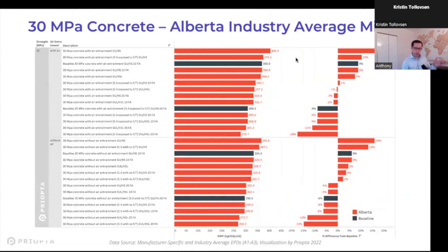Specific to the Alberta industry average concrete mix, if you look at that EPD, they have not just baseline values, but industry average values for different types of concrete mixes. For example, if you use Portland limestone cement, that's GUL instead of GU, you can see what impact that has. And then you'll see 20 FA or 10 FA, that's 20% or 10% fly ash, for example. So as you get higher on the SCM percentages, and as you use Portland limestone cement, GUL, you can see what the impact on emissions is, and how they compare against the baseline. If you don't have manufacturer specific data, you can use this during the design stage to approximate lower carbon mixes.